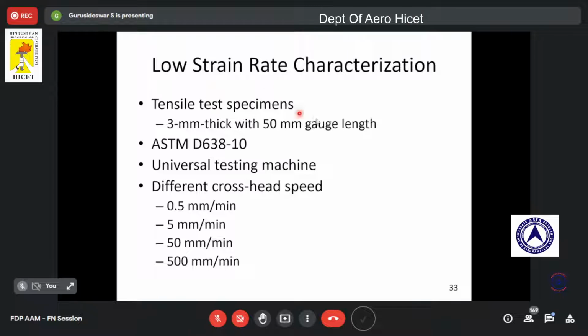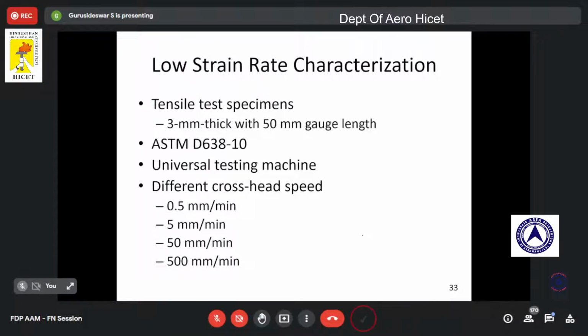For low strain rate characterization, we have used a universal testing machine, and we have done the characterization at different cross speeds. Here I can explain the strain rate. This 0.5 mm per minute is the cross speed of the UTM machine. This is the speed at which I can pull my material. Now this speed can be converted into strain rate. I need to divide by the gauge length. When I divide by the gauge length, I will get some value. That value is called strain rate. Generally we indicate the strain rate in per second, 1 by second.